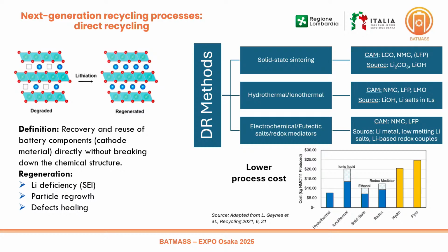One of the main causes of a battery becoming waste is that the efficiency of the material has decreased because the molar ratio, for example, of the lithium, the ion that is moving during the exchange process, is going to decrease. So the idea of direct recycling is to recharge the lithium ions inside the crystal structure in order to reform the starting one without destroying the starting active material.